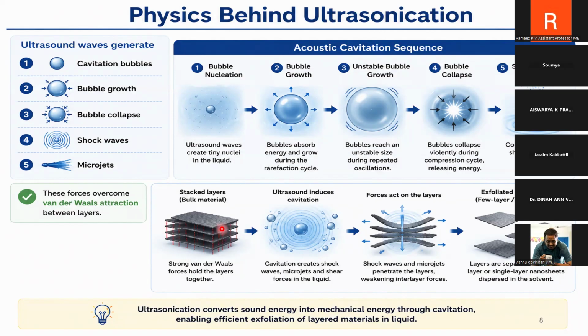That process itself is called cavitation, and that cavitation will lead to the exfoliation, which causes these layers to separate from each other. So when you choose the solvent, you make sure that the solvent possesses the same surface energy as that of your exfoliating material. That is very necessary because in our research we took hexagonal boron nitride bulk material, and why we chose isopropanol as the optimal solvent for HBN.